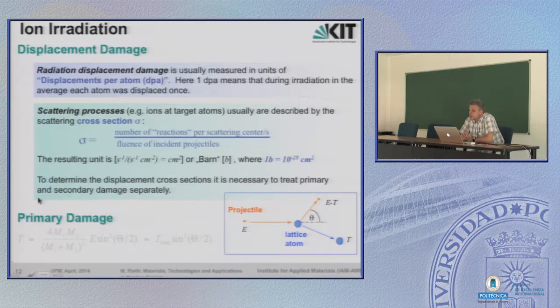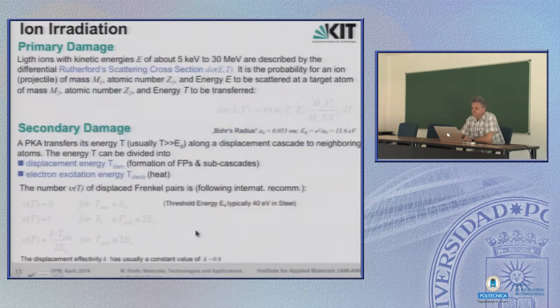To determine the displacement cross section, it is necessary to treat primary and secondary damage separately. So let's first focus on the primary damage. Remember, this was the incident projectile, the particle, or in our case, an ion. And here, the produced PKA atom energy T is given by this formula. I hope you can read it, because I had a problem with coloring on this strange software from Microsoft, but well, I don't say it too loud here on video. Nevertheless, it's a simple geometric equation, and the primary damage is closely linked to light ions with kinetic energies E, and typically they are in the range of 5 keV to 30 MeV, and they are described by Rutherford's scattering cross section.